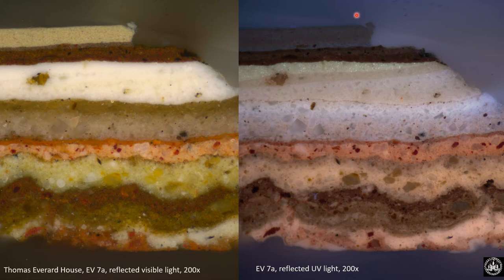And I'm showing you here two paint cross-sections taken from the Thomas Everard House that kind of show some of that deterioration and disruption. And in addition, I'm showing a visible light image as well as a UV light image. And the main reason why I'm doing that here is you can see some of these paint layers have this kind of bluish-green twinkling autofluorescence, and that's quite indicative of zinc-based pigments, which don't come into use in house paints until the mid-19th century. So for me and my work, that's using ultraviolet light and being able to identify materials like zinc white pigment, it's extremely helpful.